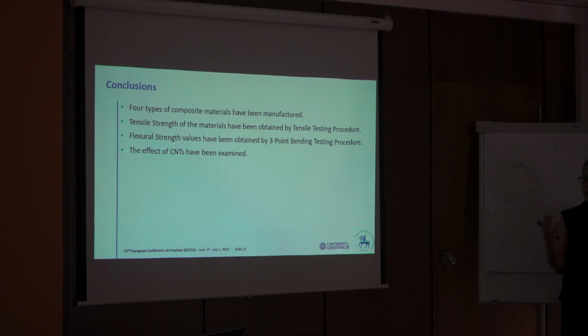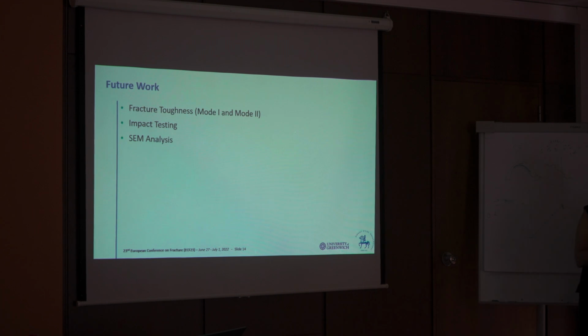So yes, we are going to check the delamination by doing some mode 1 experiments, DCB probably. And then we are going to check the mode 2 experiments too. And then we are going to run some low velocity impact testing at the beginning, and hopefully after that maybe high velocity as well. And then we are going to run the SEM analysis in order to check the fracture behavior of it.